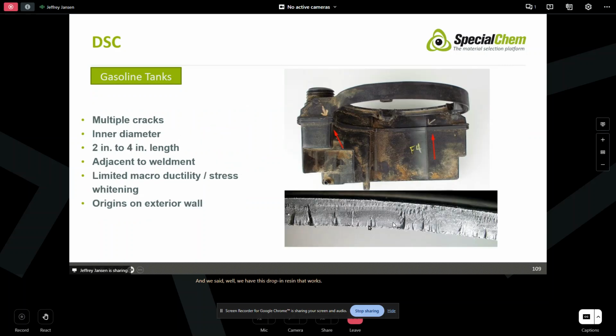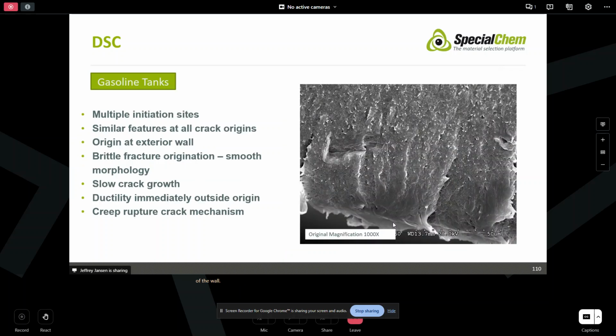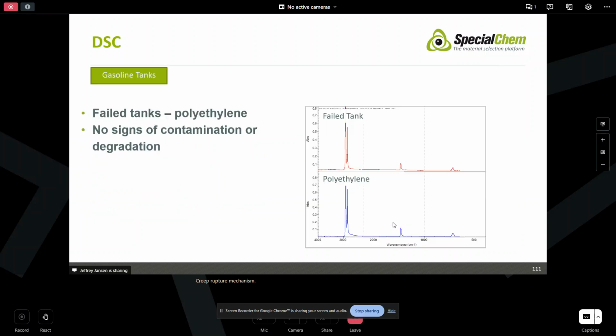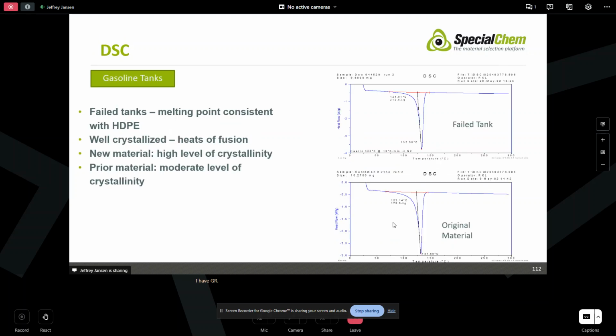We can see fracture surfaces there, limited macro ductility, some stress whitening, origins along the exterior edge of the wall. Fracture surface, again, slow crack growth, creep rupture mechanism. FTIR, just so that, basically they're both polyethylene. There were no signs of contamination or degradation by FTIR.